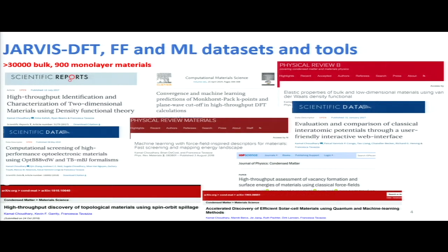So we use this very simple methodology: if it's a van der Waals material, if you use PBE, it will give you an error. Is the converse true? So if there's an error, it should be a van der Waals material, right? Very simple hypothesis. And we found that using this simple hypothesis, this method of identifying 2D materials works more than 90% accurately using the exfoliation energy calculations.